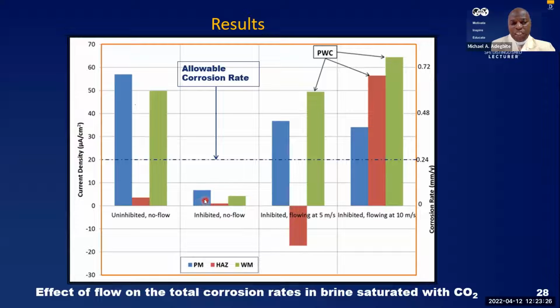And we can also see, yes, there is corrosion, but the rate is minimal, and that of the parent metal is higher rather than that of the heat affected zone and the weld metal. The heat affected zone is the red and the weld metal green. Well, that's not what we have when we have flowing condition.